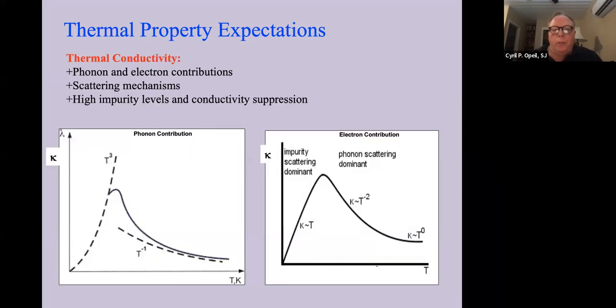Thermal conductivity: we have both a phonon contribution and an electron contribution. Because these materials are not conductors, the electron contribution is very low, so the graph on the right is really not all that dominant. It's the phonon contribution on the left side of the screen that shows. So T cubed behavior at low temperature and T to the minus one behavior at higher temperatures. What's important is that scattering mechanisms take precedence in thermal conductivity. The peak you see where the two curves meet can be much smaller depending on the scattering mechanisms. If high impurity levels are present, that peak gets squished down.